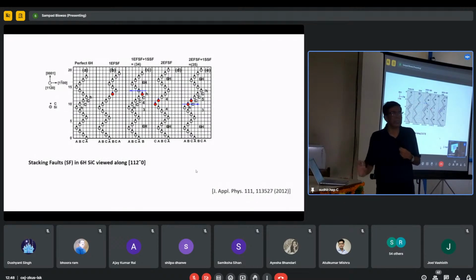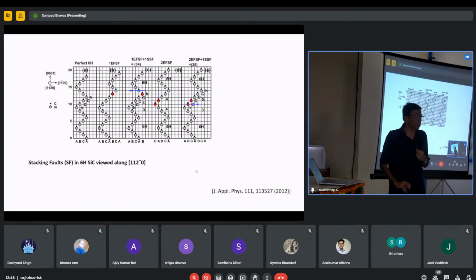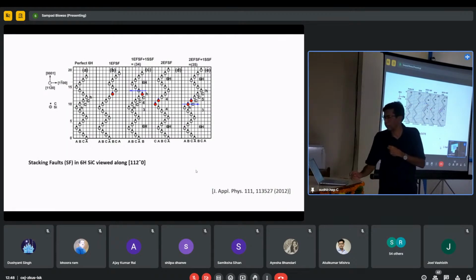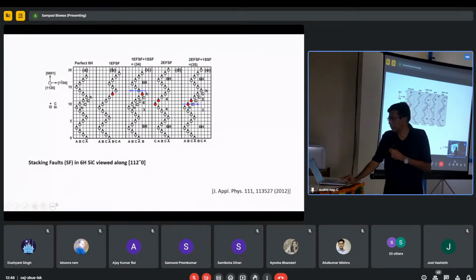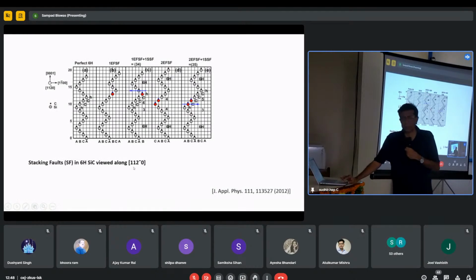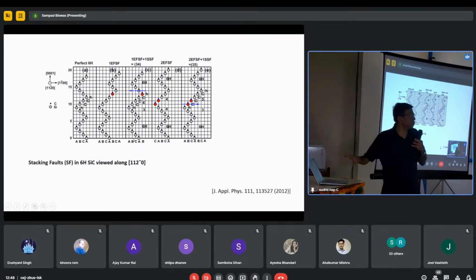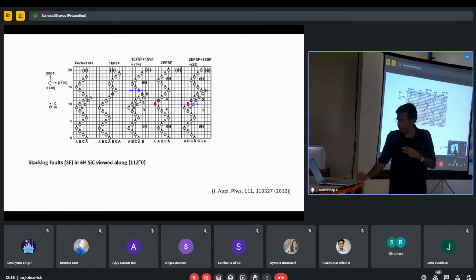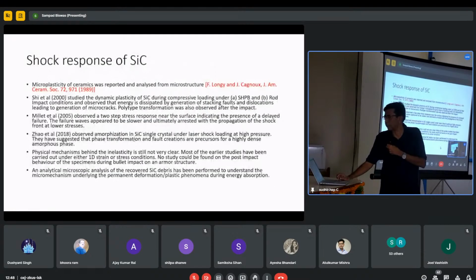Now these are the stacking faults present in the 2H, 4H, and 6H structures. Here it is a case of 6H structure in the zone axis [112̄0] and the basal plane. And you get different faults. I just wanted to show you how these stacking faults are in silicon carbide.